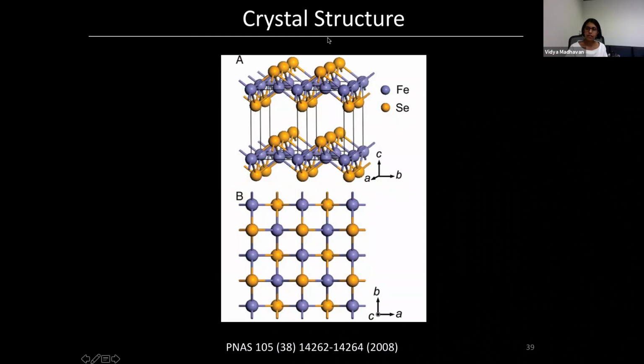And if you look at the crystal structure of FeSe, which is basically the material that we're going to study, then it's got these layers, right? Each layer is composed of one layer of iron atoms, which is shown in purple, and a layer of tellurium atoms or selenium atoms on top, and another layer of selenium or tellurium atoms below. The interesting thing is that the layer of selenium or tellurium on top is shifted by half a unit cell